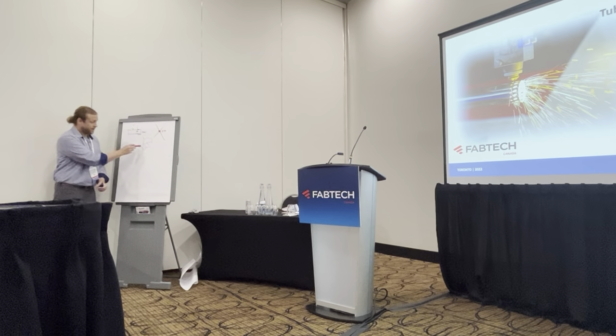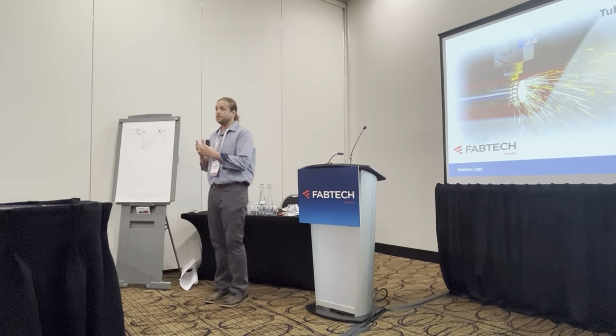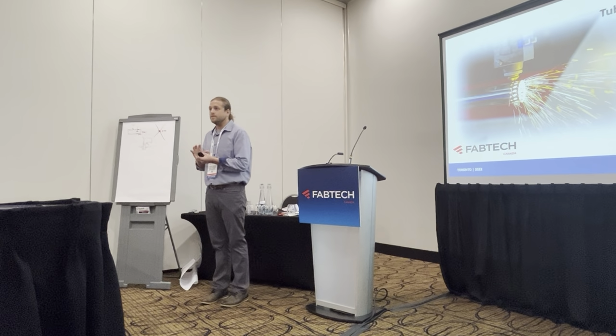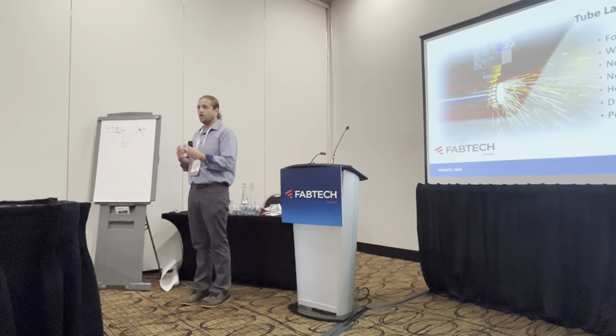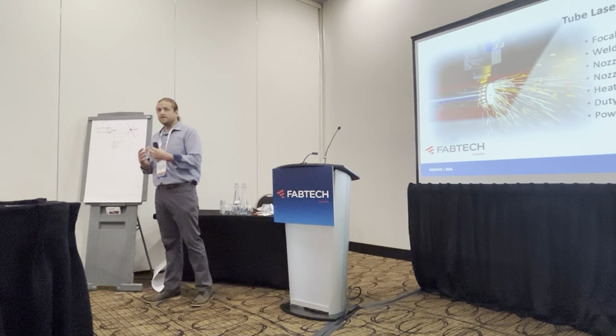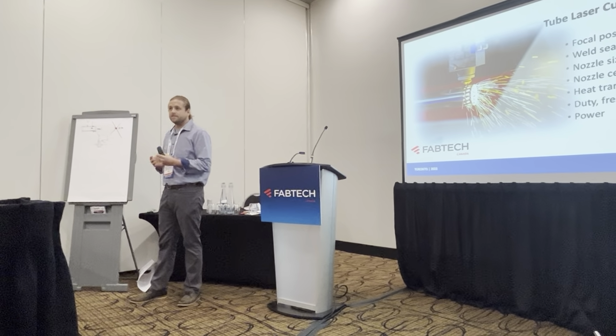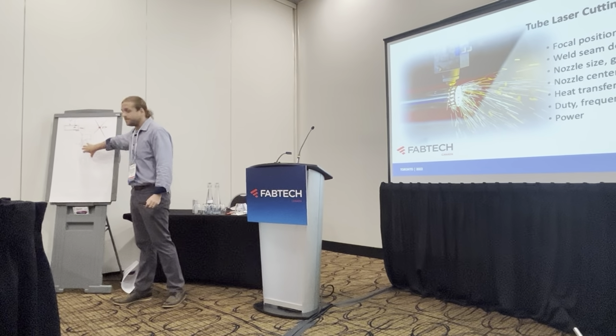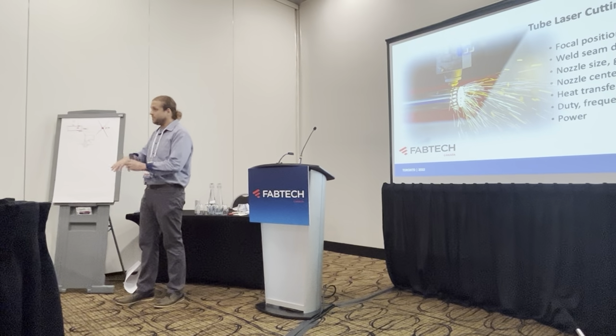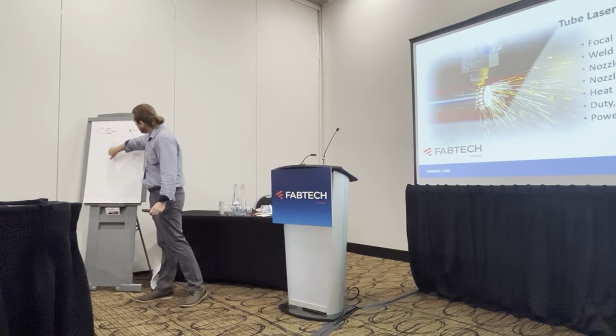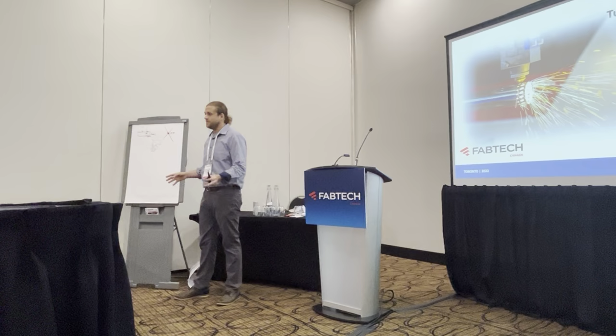If you can, you want to place that weld seam in the neutral axis, because now you're not forming or compressing that weld seam, which is a harder material. It's a heat affected zone now, because you welded it. So now that's harder material, and it doesn't stretch or compress like the base raw material does. So you always want to try to eliminate where it is. And when I say eliminate it, put it in the neutral axis so you don't have to deal with it.